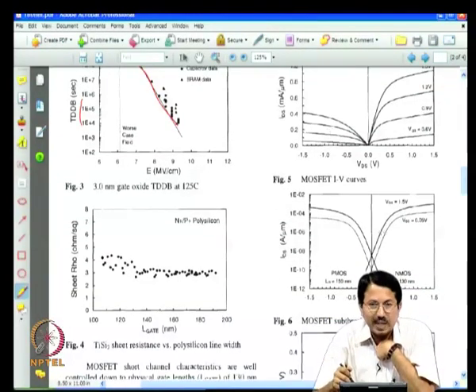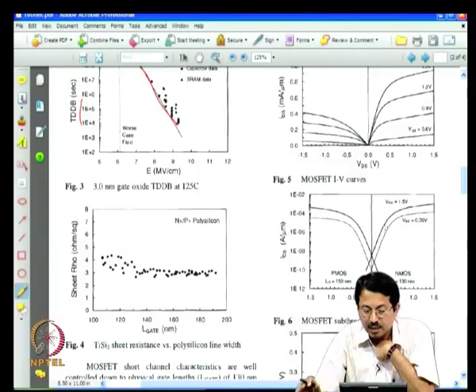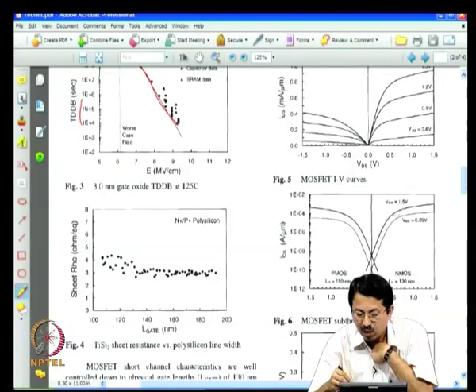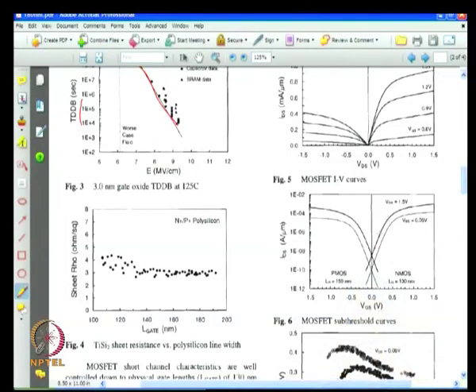This is sub-threshold characteristics. Your threshold voltage is about 0.5 volt or so, and below that, this is IDS in log scale and VGS in linear scale. It's a semi-log plot really, and this is the sub-threshold slope as we have already discussed. Notice that depending on whether you have 0.05 volt or 1.5 volt here, you will have different characteristics. That is essentially due to the DIBL effect, drain induced barrier lowering.